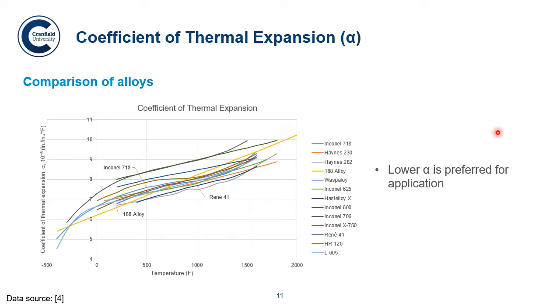So we also looked at the coefficient of thermal expansion. A lower coefficient was preferred for the application. Near the bottom we have Rene 41. Then we have 188, which again is a very straight line, very constant throughout. And we have 718, which is going through the middle again, not too much difference from the other graphs.